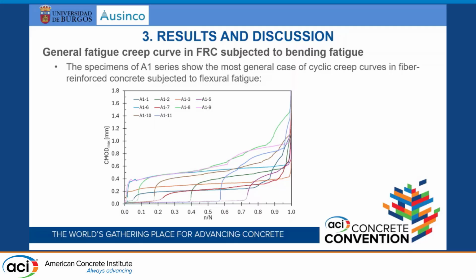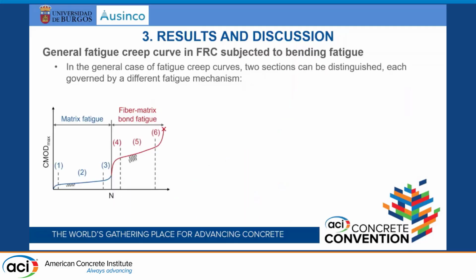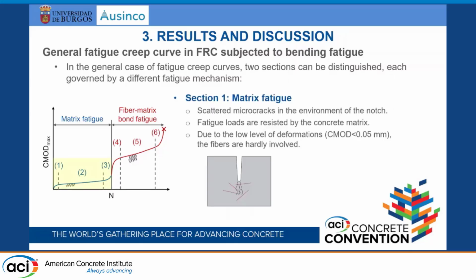Here are the same fatigue creep curves, but showing the number of cycles in relative terms. So it's better to understand and to observe the two mechanisms, this one in dotted line and the other one in solid lines with different lengths and so on. So with the example of this series, we can propose the general shape, the general behavior of fiber reinforced concrete under bending fatigue. And this is the shape, the double S-shaped fatigue creep curve that we are proposing, that we have actually observed.